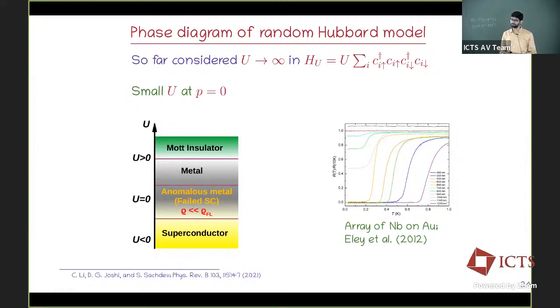So can one then think about this as a pair fluctuating superconductor? It's not a superconductor. No, pair phase disordered. I used the wrong word. Yeah, but strictly speaking, it's also not pair fluctuating, because this phase is really without quasiparticles, at least in the model that we consider. Again, we use this SYK type of model with random and all-to-all couplings, and this is really a system without quasiparticles. So you cannot even probably think of it as really a pair fluctuating phase that people try to describe in this high Tc context.